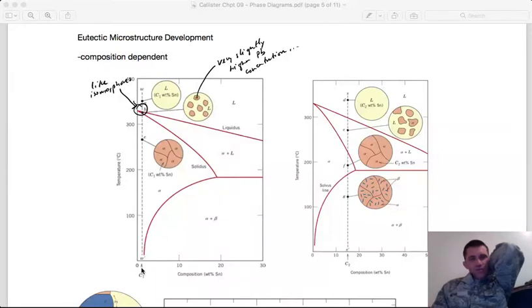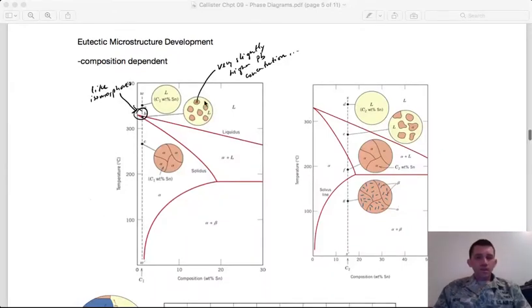we would form a microstructure that is similar to the isomorphous phase diagram. We can almost disregard the other phase, because we have such a low level that even though the solubility is limited, it's enough for the low levels that we have. So here we start off at a liquid. As we pass into the region of alpha and liquid, we will start to solidify grains of alpha phase.